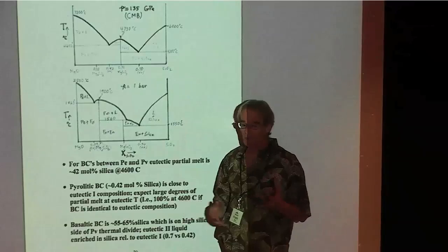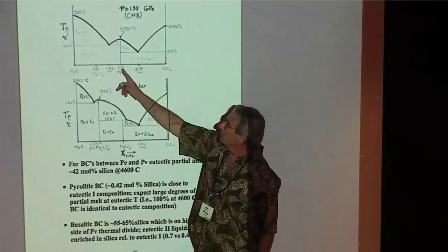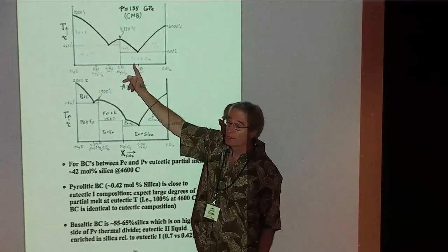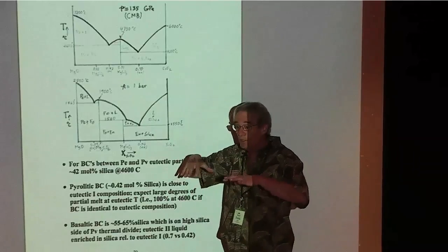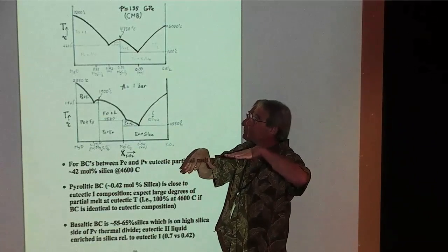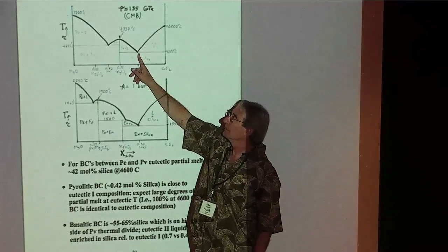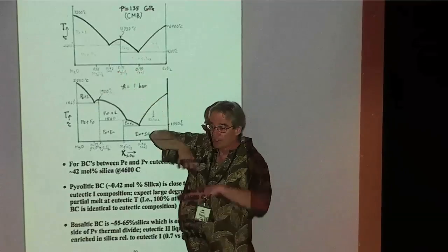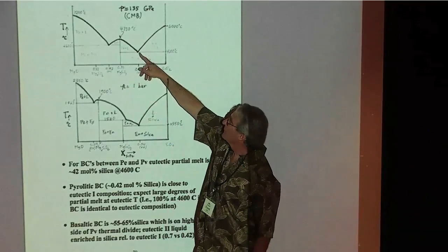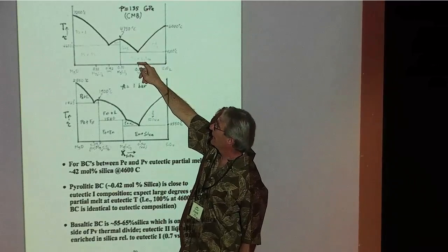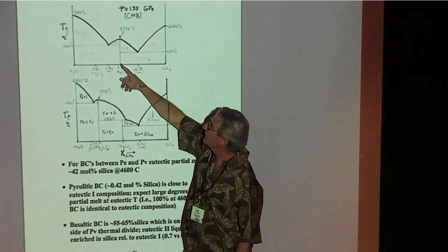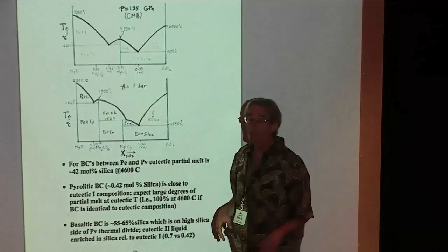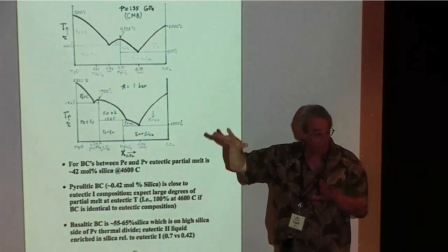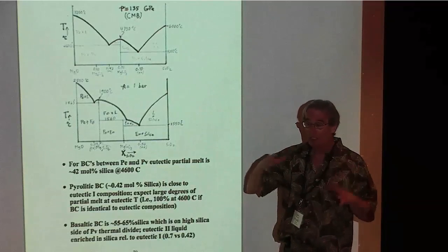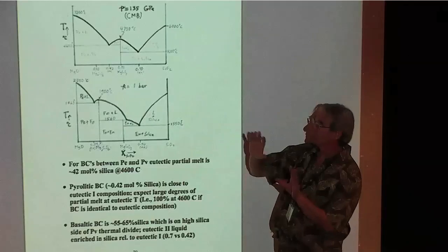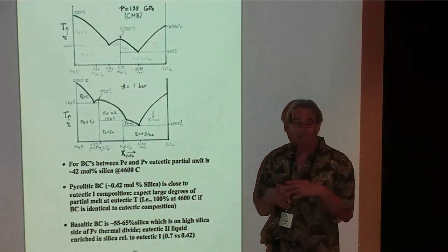So if we have this heterogeneous mantle, and this is a cartoon example here, a toy model, but if we straddled this bulk composition, some places it's on this side of the thermal divide, some places it's on that side, we could form different composition melts. Well, as a matter of fact, at low temperatures we'd only form this stuff, right? And if we could increase temperatures in the same heterogeneous block of mantle to that temperature, then the liquids here would evolve this way, and well, either this way or that way, depending on the bulk composition, probably this way actually, and we can develop some liquids here as well. So there's a possibility of having two liquid compositions of different physical properties, different compositions, different silica contents, different iron contents, different magnesium contents, so forth, kind of coexisting, right? It would be present. And then you want to inquire the density of those liquids, right?